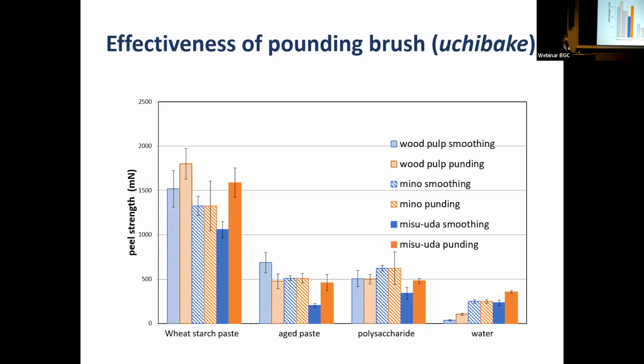We tested the adhesive force of the resulting samples in combination with Furunori and the use of the uchibake technique and brush. We found that the adhesive force increased in the samples with washi paper, that is to say samples 2 and 3, the latter two set, but that the adhesive force decreased in the samples with wood pulp paper, this one.